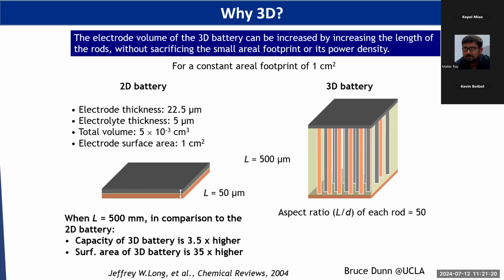But here we assume we can build high aspect ratio electrode arrays. The different colors show one is the anode, one is the cathode. We assume all these electrodes can be individually addressed, connected to the current collector. Let's say we have an aspect ratio of each rod of 50:1, which means the height to the diameter is 50:1. If you compare these two designs, we found the capacity of the 3D battery is 3.5 times higher than the 2D battery, and the surface area of the 3D battery is even more, 35 times higher.